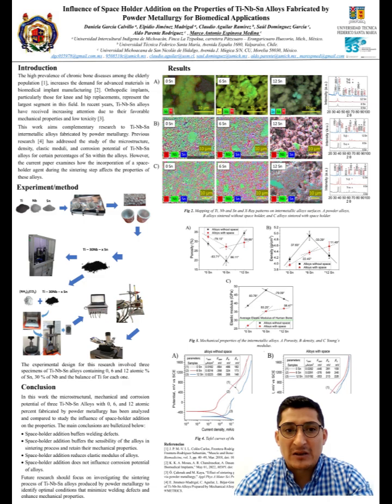The inclination of the straight lines between porosity points is steeper for samples without the space holder, suggesting that the space holder buffers the sensitivity of the alloys to the sintering process. Consequently, density and elastic moduli of the specimens without the space holder are more influenced by tin percentage than the other ones. Alloys with the space holder exhibit elastic properties closer to those of human bones. Enhanced porosity and surface roughness could improve cellular responses, as suggested in scientific literature.